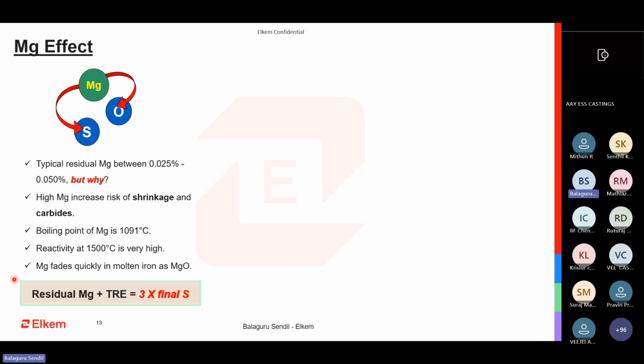So as I told in the previous slide, the nodularizing elements are cerium and lanthanum as well. Be it any nodularization process you use, it could be FSM, it could be cored wire, it could be pure magnesium, it could be in-mold treatment, there is always rare earth attached to it. There are very few cases where you have a zero rare earth based nodularization process. So it is better to add all these three things and then see how much residual Mg is required.